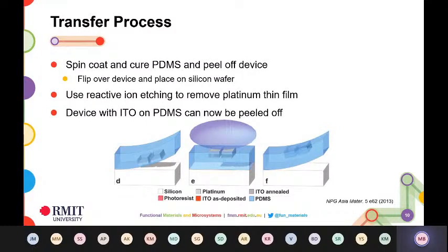And when you peel it off, what is essentially happening is because the platinum is not stuck very well to the silicon, the entire layer just comes off along with the oxide adhered onto the PDMS. So when you flip it, you have your PDMS, you have an oxide layer on top of it, and then you have the platinum sitting on top of it. You get rid of the platinum using an etching step, and you're left behind with your oxide semi-embedded or half embedded on the PDMS substrate. And that's your way of transferring your oxide thin film onto a PDMS substrate.